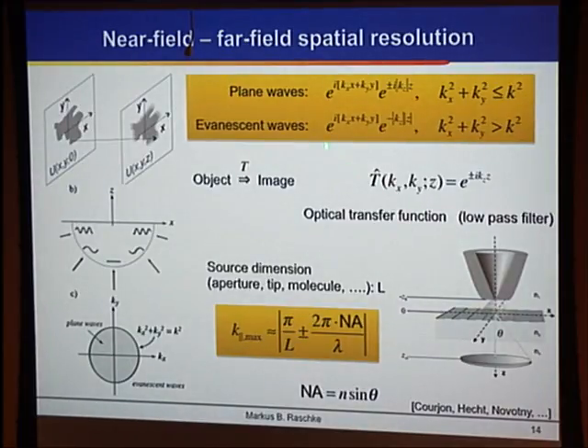If you, however, consider also all the evanescent waves, so essentially if you're trying to do the image reconstruction close enough to the object where your evanescent modes have not completely decayed yet, then you can, in some way, with arbitrary precision, reconstruct all the evanescent field distribution around the object, and then you can essentially get arbitrary spatial resolution, as long as your probe or the detector is within a distance of the object of a characteristic dimension L and is correspondingly small. And this is why your far field equation turns into this near field analog, where it's wavelength independent, and this is why we get the same spatial resolution whether we image in the UV or in the terahertz, over many orders of magnitude different wavelengths, because now we are completely determined only by the dimension of this tip apex.